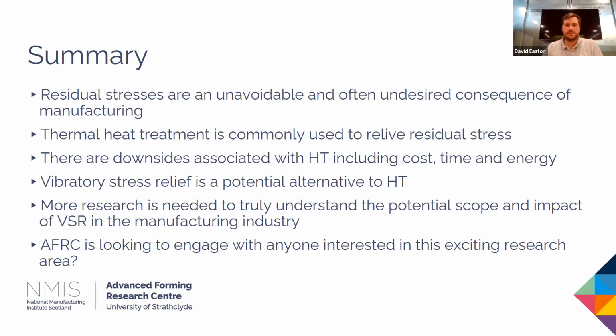So to summarise, residual stresses are an unavoidable and often undesired consequence of manufacturing. Thermal heat treatment is commonly used to relieve residual stress and has been for a long time. Despite this, there are downsides associated with heat treatment, primarily cost, time and energy. And if we look at VSR, this offers a real potential alternative to heat treatment. And in some circumstances, we can alleviate those downsides, and the cost, the time, and the energy doesn't become an issue.